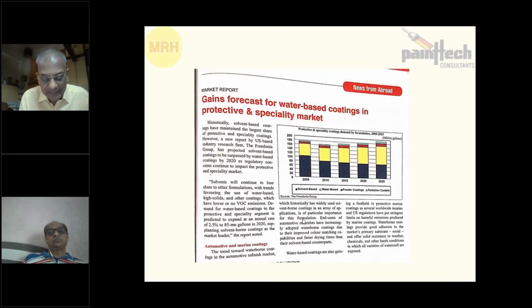Now, you'll be surprised to know I have been doing R&D on this for the last 31 years, since 1989. With more water, I made one cement primer very successful at 1:1—a normal solvent-based cement primer, 100 liter primer, you can add 100 liter water successfully, with no dryers, because if you add dryers they precipitate at such high water concentration. I intelligently use a little zinc oxide, so zinc oxide forms zinc soap with the alkyd, and drying can be achieved.